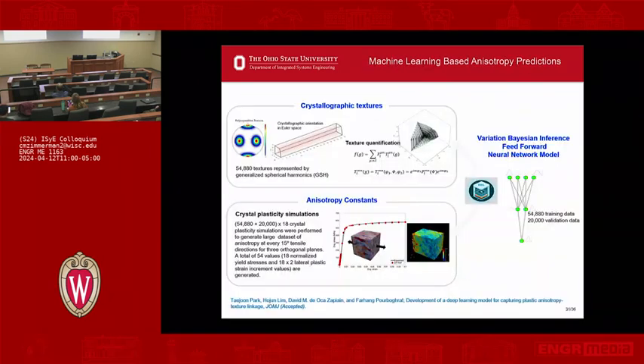Now, again, as I mentioned, this is all to be able to create a trustworthy machine learning type of model based on these things. And what we did is, we know that these little green, red things that I showed you are called texture and orientation. You can basically come up with 3 parameters that give you any type of orientation that potentially could be available to any kind of metal. So within that 3-dimensional space, the red cloud that you see in here are points of those orientations that we took, all sorts of combinations. In fact, we generated 75,000 data points of these orientations.